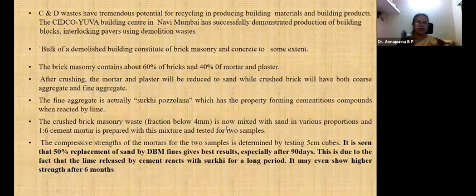The crushed brick masonry waste below 4 mm is used to replace sand in various proportions, and 1:6 cement mortars were prepared and tested. Five centimeter cubes were cast and then tested. It is seen that 50% replacement of sand by DBM fine gives the best results, especially at 90 days. This is due to the fact that lime released by cement reacts with surkhi over a long period. It may even show higher strength after 6 months because of the presence of the lime. Okay.